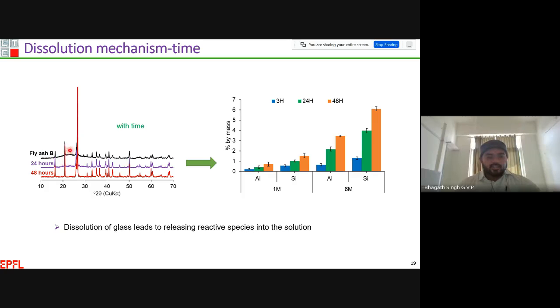This is the XRD spectra of fly ash B, and this is the XRD signature at 24 hours. This is the XRD signature at 48 hours. As you can see here, from 0, meaning initially, to 24 hours, you can see a reduction in the amorphous phase. From 24 to 48 hours, you can see a completely dissolved amorphous portion without affecting the crystalline phase. Then I tested two environments. One is a 1 molar alkaline environment, another is 6 molar. I focused only on alumina and silica, as these are the predominant phases present in our fly ashes.